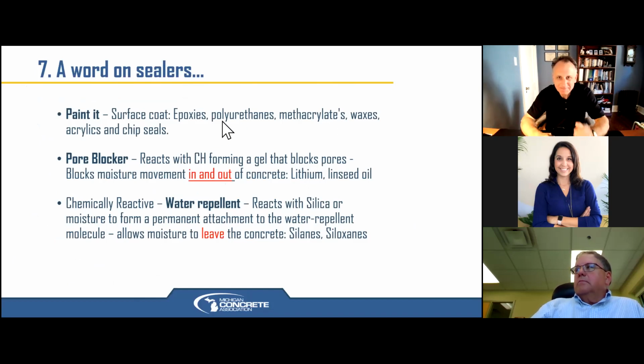You can buy a paint, which is methacrylates, waxes, acrylics, chip seals. We can paint a surface, that'll seal it. Pore blockers are chemicals that we put on that react with the calcium hydroxide in our concrete and form a gel that blocks moisture. But it basically caps it, keeps the moisture in, and won't let moisture leave or come in. Some of the products you've heard of are lithium-based materials or linseed oil, the old boiled linseed oil that we used to put on bridge decks in the past, kind of a pore blocker type.